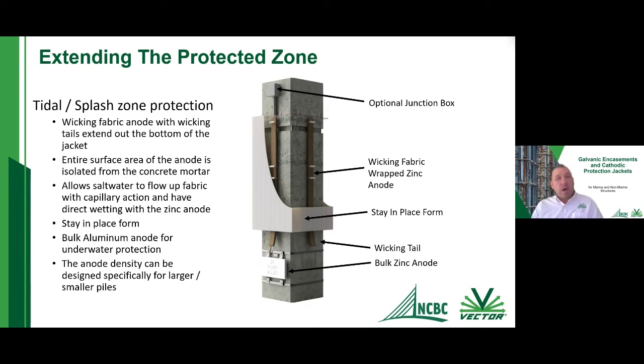So you can basically run these wires from all of the anodes to the junction box, and then you can have some wires from your reinforcing steel to the junction box, and that allows you to monitor the jacket system to see how much current it's actually producing, and basically measure the life expectancy as well of the system. It's also used for energizing, turning on the jacket, and collecting some data up front to show that the jacket was also installed appropriately. But with all of this, we're getting some increased cathodic protection for it. And here on the next slide, I'm going to just show you how it works.